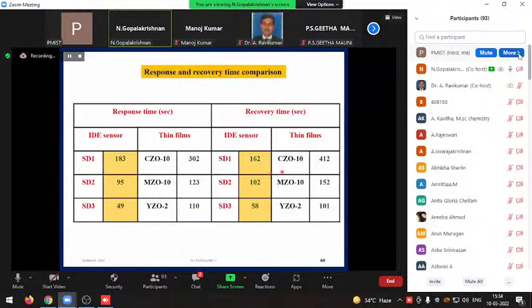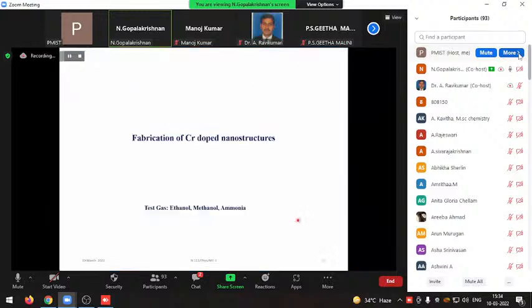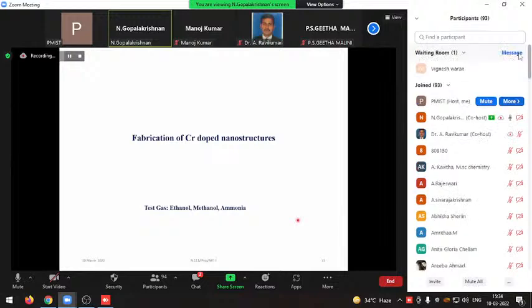See again the response and recovery time. In this case, maybe only in this IDE sensor, only 183. Maybe here it is a little bit low. In this case, maybe a little bit low here. And then in this case, this is 95. You have 102, 49 and 58, 302 and 412, 123, 152, 110, 101. So the two cases are almost more or less equal for response and recovery time only. Our results are justified already. So that was the overall summary. That means the IDE sensor is more efficient than the thin film sensors.